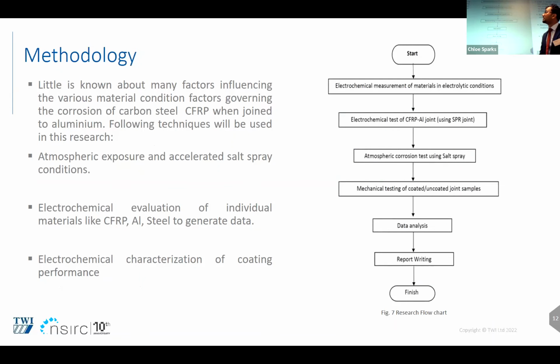Coming to how I'm going to proceed. As I said, very little is known about the factors influencing the various material conditions governing the galvanic corrosion between CFRP and carbon steel and aluminum. So I'm going to use the standard tests such as atmospheric exposure, accelerated salt spray test, and electrochemical evaluation of materials like CFRP, aluminum, and carbon steel to generate data on how these things behave in a corrosive environment, which will be seawater or 3.5% NaCl. Electrochemical characterization of coating performance will be done by using different characterization techniques such as XRD, XRF, and SEM.